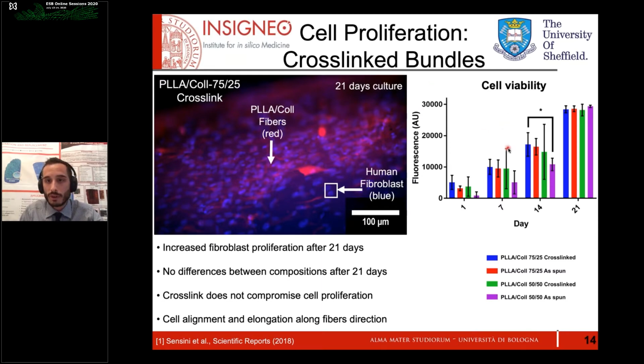What you see from the cell viability test is that after 21 days of culture, the fibroblasts proliferate on all the different blends, showing that cells like these materials. And on the other side, the cross-linking process doesn't have any toxic effects on cell proliferation.